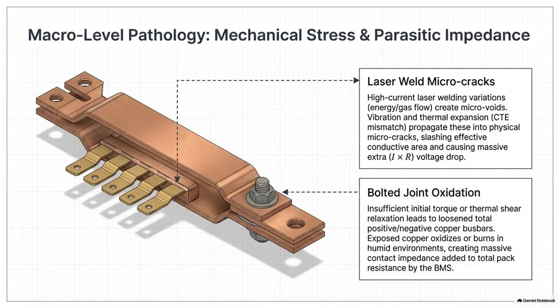If the laser focal length shifts by even a fraction of a millimeter, or if the peak power fluctuates, and this happens if the flow rate of the argon shielding gas is just slightly off, the keyhole dynamics become totally unstable. So what happens to the weld? The vapor cavity can collapse prematurely, and it traps the shielding gas or the metallic vapor inside the molten pool. Oh, so you get bubbles. Yes. When it solidifies, you are left with microscopic voids, air bubbles inside the weld. Or, worse, you get what's called a false weld or a cold weld.